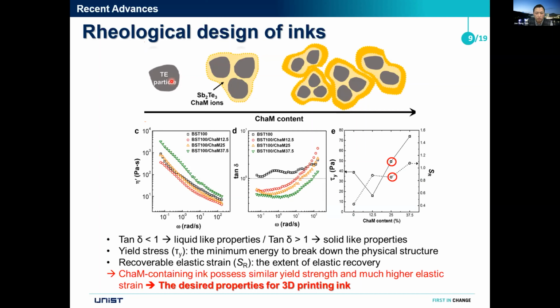This particle charging is beneficial for getting a good colloidal dispersion in an electrostatic manner. Also, this particle has a larger hydrodynamic volume fraction in the ink, which can increase viscosity and elasticity in the ink simultaneously. So our ink has higher viscosity and elasticity, which are desirable for the 3D printing process.